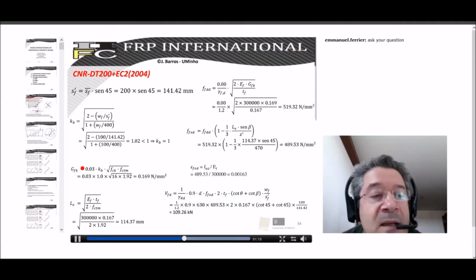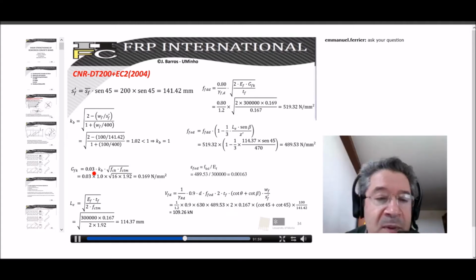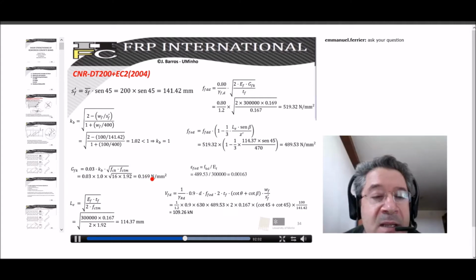So that depends on this kappa b parameter, so we start by evaluating the kappa b parameters that depend on the geometry of the strengthening configuration that we are using. So this is the width of the strip, and this is the spacing between the strips, and then we obtain a kappa b factor that is 1.02, but since it should be lower than 1, we are adopting the value of 1. And this is the characteristic value of the compressive strength and the average value of the compressive strength. And then we obtain for the GFk the value that is 0.17 megapascal.